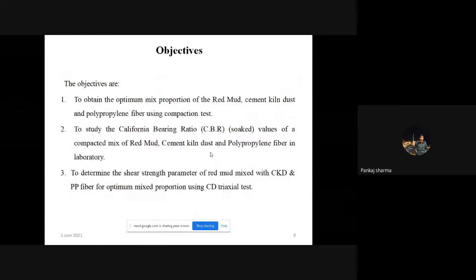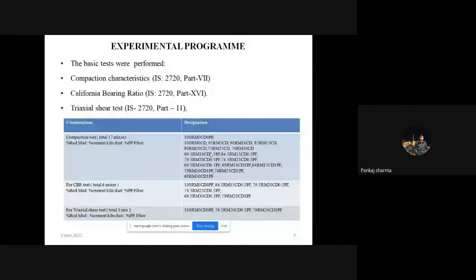The objective of the study is to obtain optimum mix by using the light compaction test. Similarly, to obtain the California bearing ratio capacity of different mixes, and to obtain the shear strength parameters of the optimum mix. Here is the experimental program. From the table, it is clear that different tests are carried out on red mud with cement kiln dust percentage from 0 to 30% at an increment of 5%, along with the polypropylene fiber 0 to 1%. From here, it is clear that we are first using pure red mud, then we use red mud along with cement dust, and then we use the red mud and cement dust with the change in the fiber percentage.